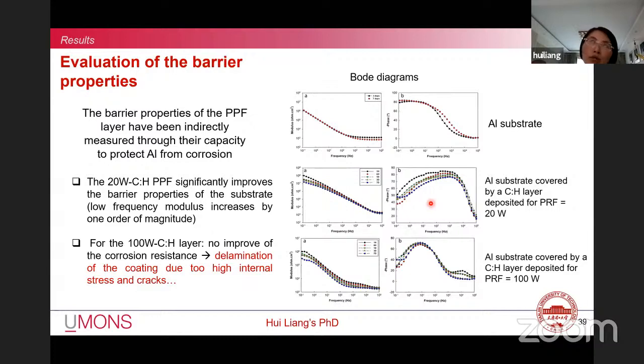Here we use the sputtering work power of 20 W to prepare the plasma polymer ethylene layer, which is used to cover the aluminum substrate. After immersion for 7 days, comparing the first figure and the second figure, we can find that compared with the uncoated aluminum substrate, in the low frequency, the aluminum substrate covered by the 20 W power layer shows better anti-corrosion performance. So the 20 W CH plasma polymer film significantly improves the barrier properties of the substrate.